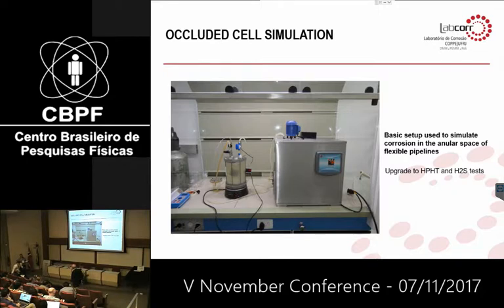We can use different mechanical tests such as low strain rate tests, constant load, and you can control the H2S partial pressure, different gas compositions, and we do the ordinary tests.